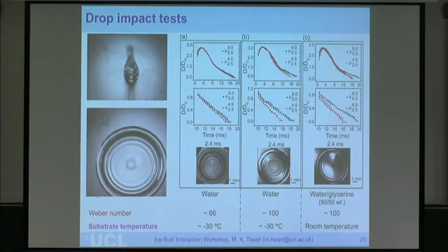So this is trying to plot the diameter of the contact between the droplet and the solid surface with time. As we would expect, as the droplet hits down, it spreads quite rapidly due to inertia, and then the surface energy has to get back, which means that it starts to recoil, and the recoil is slower now because the viscous dissipations have kicked in. And what you see quite dramatically is towards the end stages between the two surfaces that I'm noting here.